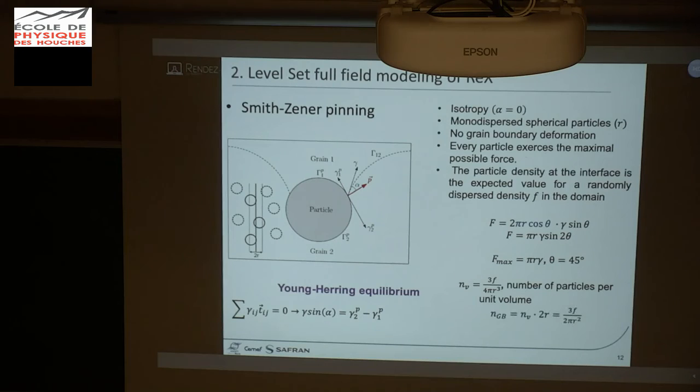But with this main field equation, you can obtain the classical, well-known Smith-Zener pressure of a given statistical description of the second phase particles in a polycrystal microstructure. And with this classical Zener pressure, you can also obtain an equation defining a limit mean grain size of the polycrystal during grain growth due to the presence of a second phase particle population.